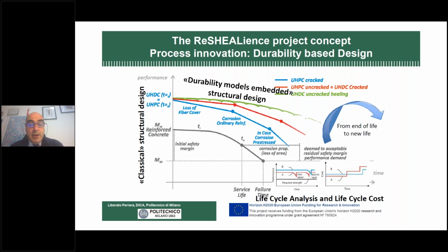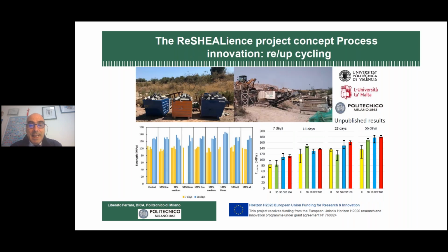Obviously, with this material, your end of life is quite long, more than 100 years. So you may ask, what does it mean? More than 100 years, because in that time, the contractor, the owner, the end user may go into changes of its needs. So we have addressed also the recyclability of our material. I will say we were a zero waste project because all the specimens which were produced in our lab were completely recycled, and we demonstrated, if we look at the graph on the right, with reference to the parent material,